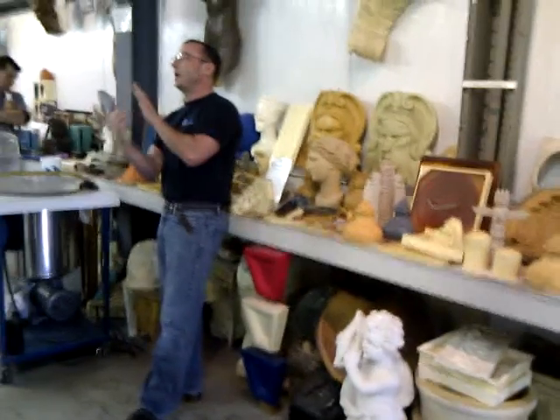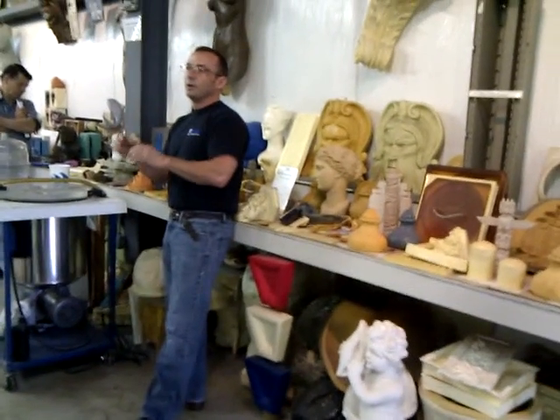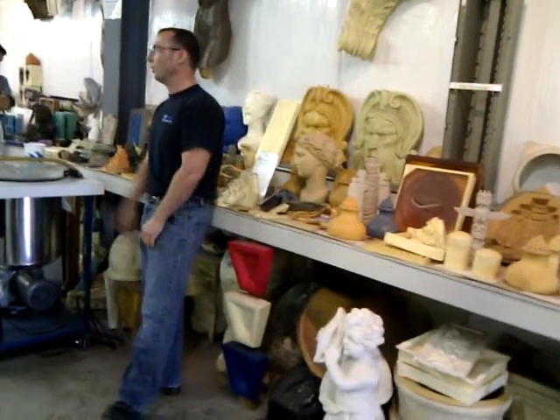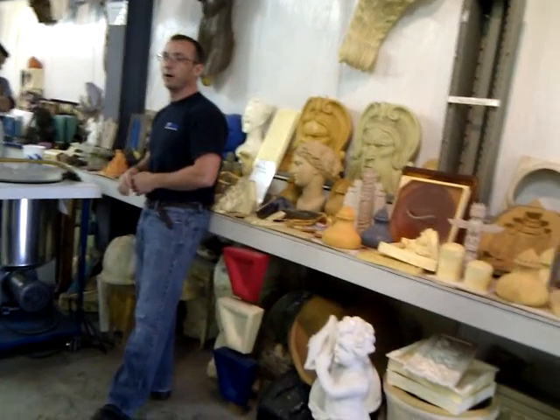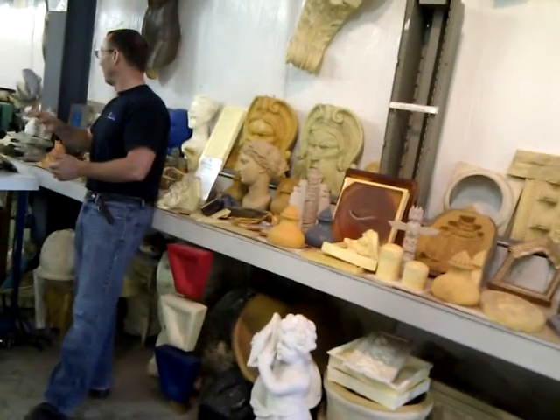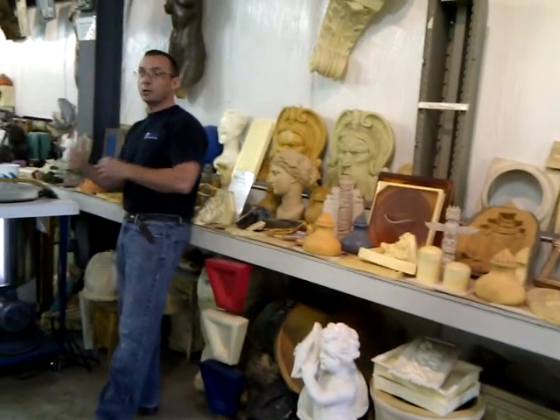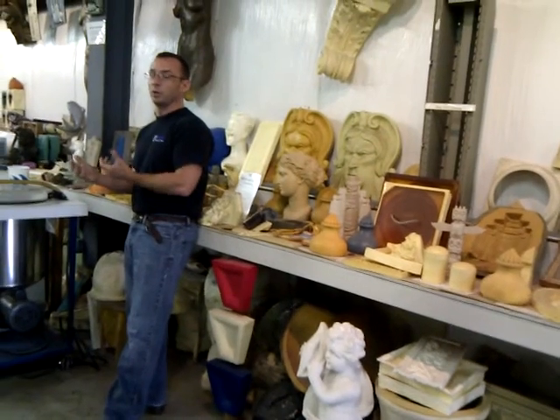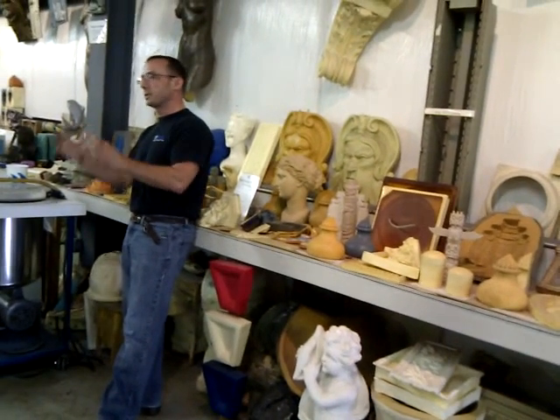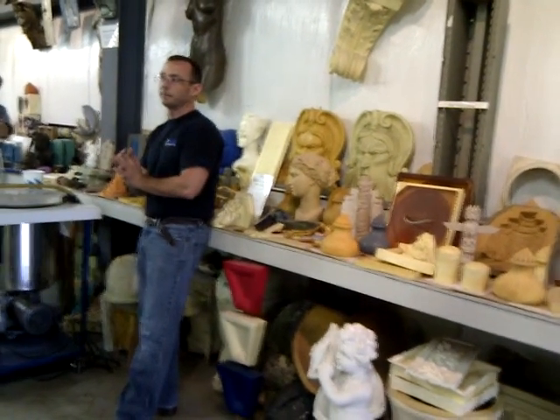attack the resin that's around the metal particle, but it can't get to the resin that's behind the metal particle. And so it's a really slow deterioration process with bonded bronze. What ends up happening is the part patinas and dulls naturally outdoors just like a real bronze statue would, and so that actually protects the resin from the UV light.